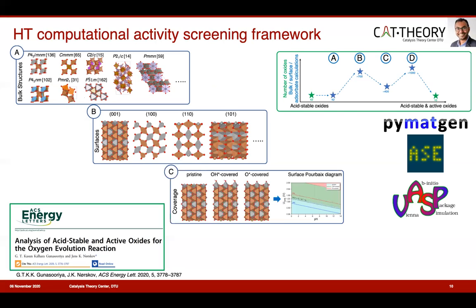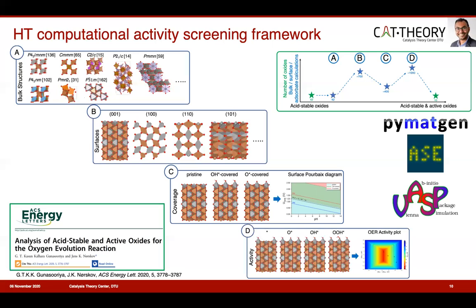Then the coverage of reaction intermediates may significantly impact the local environment of the active site, resulting in changes in the adsorption strength of the intermediates. So to determine the most stable surface coverage, we construct surface Pourbaix diagrams at three extreme coverages: pristine surface, OH covered surface, and O covered surface. And then we construct the surface Pourbaix diagram, and we use the surface structure corresponding to the most stable coverage at 1.6 volt versus RHE for further activity calculations. Then we determine the theoretical thermodynamic OER overpotential, which is a measure of the activity of a catalyst.